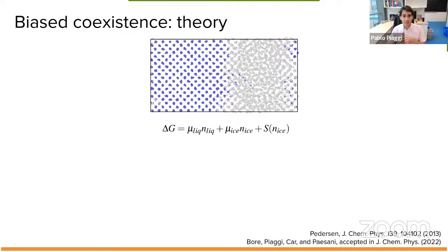And the next method that I'm proposing is the biased coexistence method. And as I described before, here we have the liquid in contact with the solid. It could be other phases. In this case, I'm considering those two. And the idea is to write the Gibbs free energy in the following way. We have the chemical potential of the liquid times the number of liquid-like atoms plus the chemical potential of ice times the number of ice-like atoms plus something that is connected to the interface.